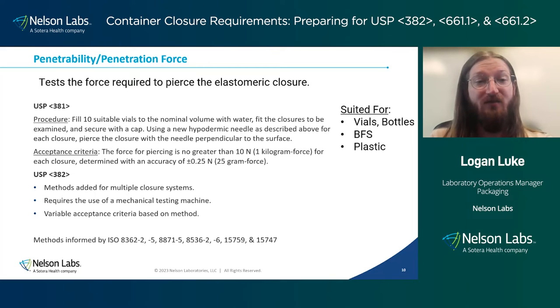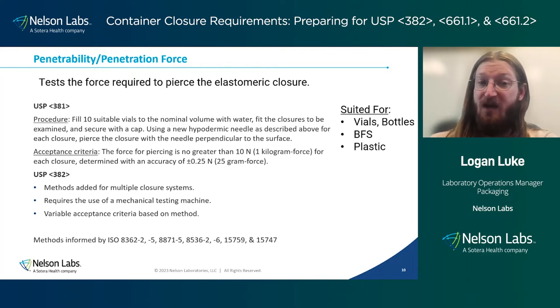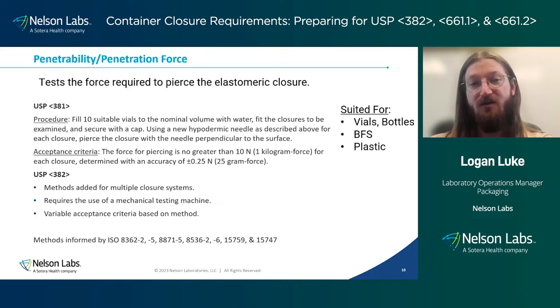Now it requires the use of a mechanical testing machine, and your acceptance criteria is going to be different based on whether you're testing a vial, bottle, blow-fill seal, or bag. The sampling rate of your machine has to be at least 100 hertz, and your crosshead speed has to be at least 200 millimeters per minute. The guidance given for acceptance criteria is meant for ease of access. So that could be different based on what you're using, and it's up to you to determine what that ease of access number looks like.